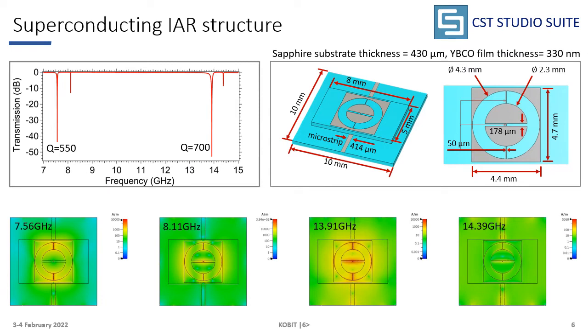The superconducting inverse anapole resonator structure is obtained by creating a 50 ohm microstrip on a 10 by 10 substrate with YBCO coating on both sides, and then the inverse anapole resonator pattern on another 8 by 5 millimeter substrate with YBCO coating on just one side. The hybrid structure is obtained by placing the inverse anapole resonator chip on top of the microstrip. All of the geometric parameters are optimized by taking into account the field distributions, resonant frequencies, and quality factors of the modes using the CST Studio Suite.